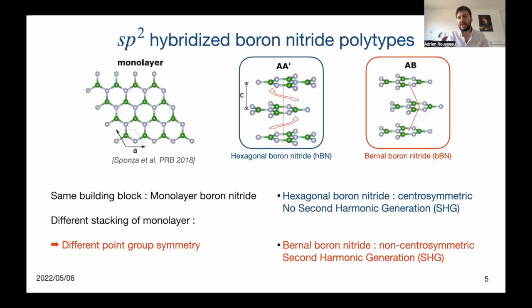Among the sp2 hybridized polymorphs of boron nitride exist different polytypes, which differ by the stacking of the same sp2 hybridized honeycomb layer of boron nitride, also named the monolayer boron nitride, whose atomic structure is represented here on the left. The most commonly observed polytype is hexagonal boron nitride, which consists of alternatively 60-degree rotated layers where the boron and nitrogen alternate along the c-axis, namely the AA' stacking.